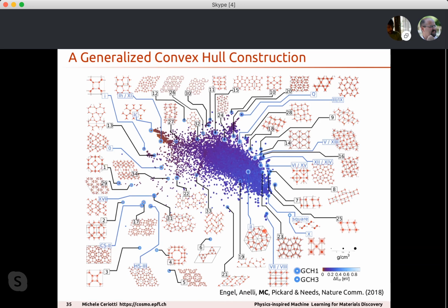Not only do you get, out of the 100,000 structures that came out of the random structure search, all of the 17 known phases of ice, but also 17 phases that might be stabilizable somehow. To give you an example, we get a couple of structures that are known clathrates. This is a pure water phase, so it is just a cage, but it is the cage that, using a templating agent such as methane or some other small molecule as a perturbation, can be made locally stable and therefore synthesizable.